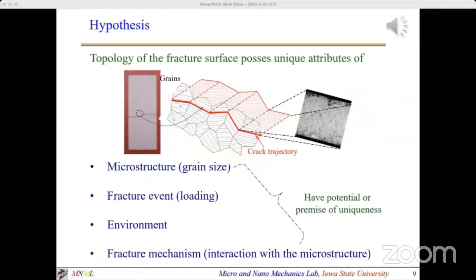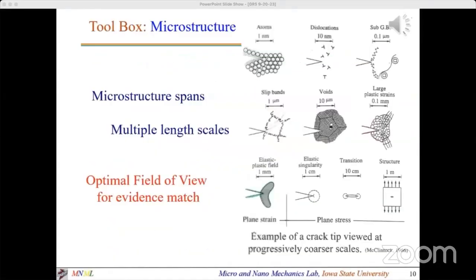The topology of the fracture surface possesses unique attributes which we can quantify. The fracture surface topology depends on grain size, loading direction, environment, and how the material fractures. At what scale should we view the crack to show the individuality of the event? At the nanoscale, a crack is a bunch of separated atoms emitting dislocations at 10 nanometers. Dislocations cluster at 100 nanometers into slip bands at 1 micrometer, forming voids within the grains at 10 micrometers and progressing to the structure scale. The question is, at which scale should we view the crack surface?